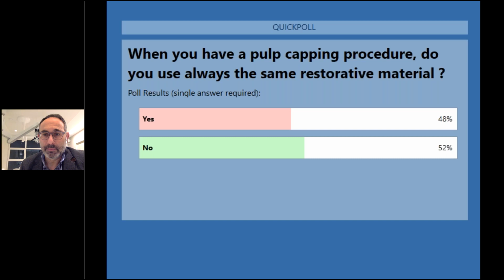When you see that half of the attendees are using the same restorative material, do you mean the same restorative as a pulp protection, or combining two materials together? The same for the pulp, just pulp capping, not combining, just one material. I think this can also be done, but then we need to think about the final restoration, because you also need to avoid having a lot of interfaces and getting the patient back to open and remove the temporary and then put in the final restoration. We can help the pulp, but we can hurt the pulp if we open again and deliver anesthesia, and the risk is to break the dentinal bridge that is starting to form. This is the problem if we do it in two times.